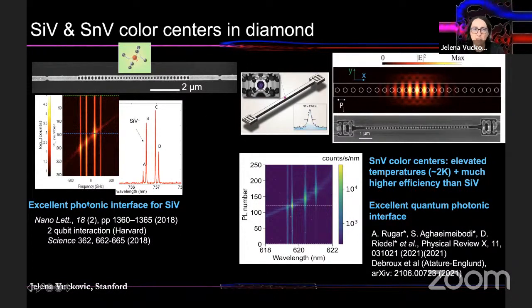And a lot of effort has been done by our group and many other groups on silicon vacancies in diamond, including excellent quantum photonic interfaces and also 2-qubit interaction with the same cavity at Harvard. Tin vacancy in diamond is a more recent color center that we and others have been looking into, and we're more excited about tin vacancies than silicon vacancies because you can achieve pretty much all of the advantages of silicon vacancies, embed them in good photonic structures, have good coherence time, but even at slightly elevated temperatures, you don't really need to put them in a dilution refrigerator as you need to do with silicon vacancies. And also you have higher internal quantum efficiency to begin with, which is also very important. So recently we demonstrated a quantum photonic interface for tin vacancy in diamond, which means we really coupled this artificial atom to a single mode of the cavity.